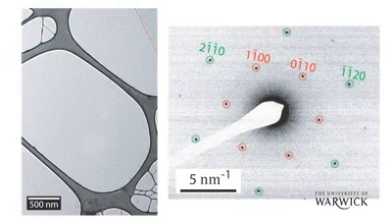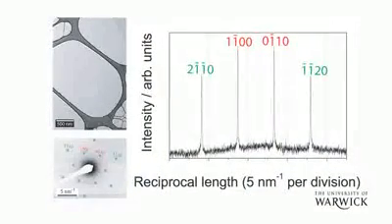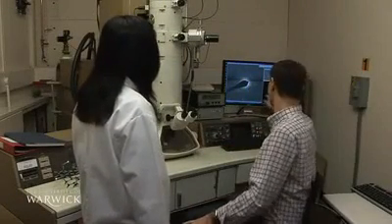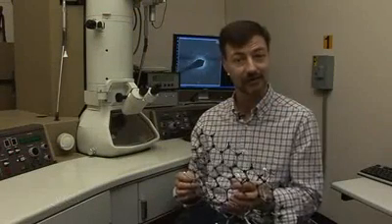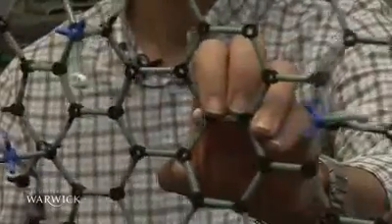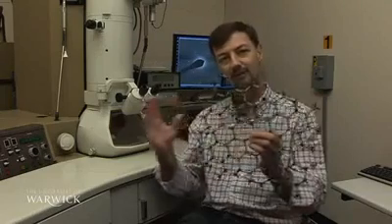Electron diffraction shows a distinctive hexagonal structure. The inner spots are more intense than the outer ones, which, as we discussed in the paper, is a distinctive signature of single layer graphene. We can learn more about the structure of a graphene-like sheet by using electron diffraction, and in particular as we tilt the sample in the microscope. The spots move as you tilt the sheet because the projected distance gets smaller as you tilt, and so the spots move out.